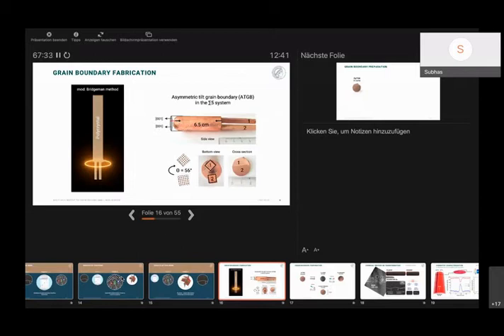Yes. So, yes, it can form a sigma 3, and we did this also already before. However, for the sigma 3, you need different zone axes. So it depends on how you arrange the seed crystals. Depending on how you arrange the seed crystals, that's how you determine what grain boundary you will grow. It's not necessarily always the exact one. As I said, it's sometimes hard to predict what actually forms. But in principle, if you set up the two seed crystals correctly, you can determine what grain boundary grows. And we did this here with the 110 growth direction, 110 zone axis, which is the tilt axis of the sigma 5 grain boundary.